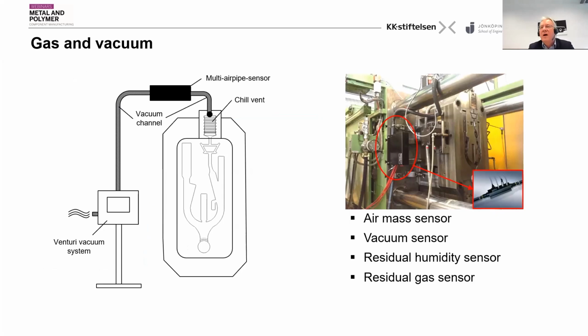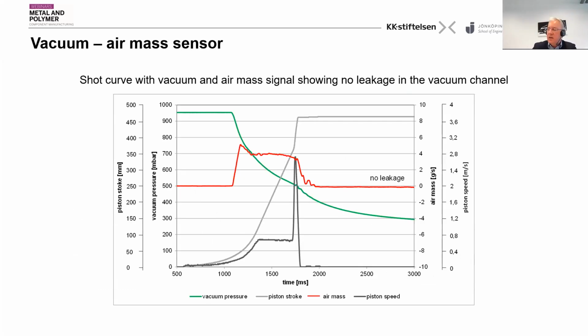Anders already mentioned vacuum. This is very important, and we use vacuum processes, but also classical standard vacuum processes. And what people measure here is basically only the pressure in the cavity. But here we have a multi-vacuum pressure sensor, and it measures the air mass which you take out of the mold, the vacuum pressure, and the humidity of the air, and this is very important.